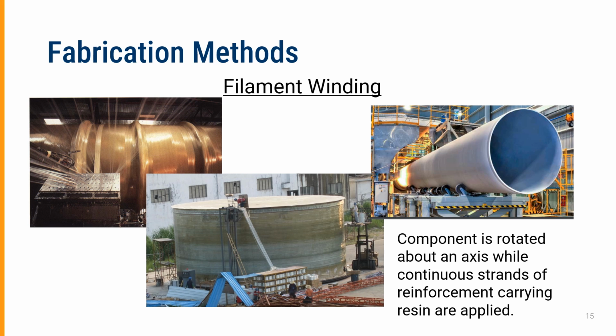This can be used to provide fairly significantly stronger FRP, and as well we can change the rate at which this carriage travels in order to alter the helix angle, which can give strength properties in different directions.